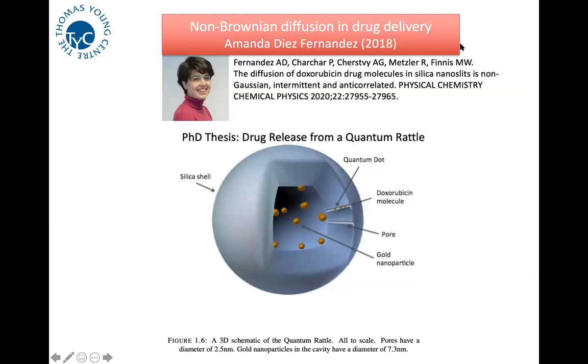here's a diffusion problem that Amanda, a student with us, did a few years ago, starting off a PhD thesis on an interesting problem on a drug delivery system. This was in Molly Stevens' group. They were looking at these little porous silica spheres, which actually had gold particles in them. So they were called quantum rattles, and they were 100 or so nanometers across. And they could pick up quantities of doxorubicin, a cancer drug, and deposit it again. And it was diffusing through these little pores. And we did some quantitative modeling comparison with the experiment, but realized we didn't know what the diffusion coefficient of this molecule was. So we'll just check it out by doing some molecular dynamics calculations.